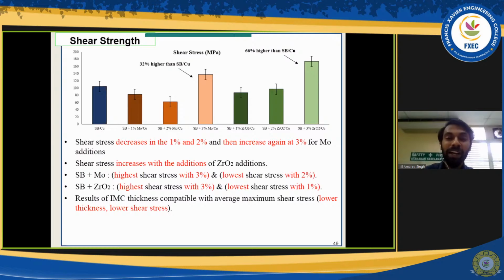Not only that, there were no molybdenum nanoparticles at the interfacial layer. Just to share with you guys, there were no molybdenum nanoparticles. There were compounds of molybdenum. That means the molybdenum has reacted with the Sn and produced MoSn. So the nanoparticles were not there to block the diffusion or to actually restrict the shear strength. But interestingly, when we look at the zirconia, in all three zirconia additions, even though some zirconia has diffused or reacted with the tin or copper, there was still presence of nanoparticles of zirconia itself.